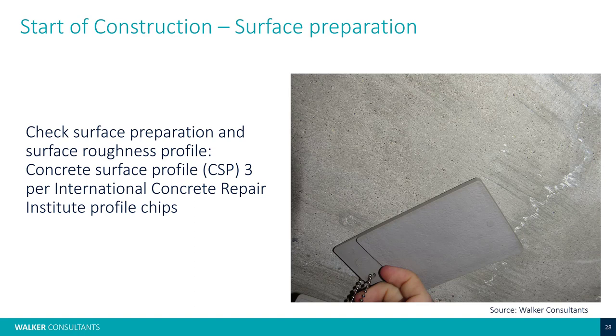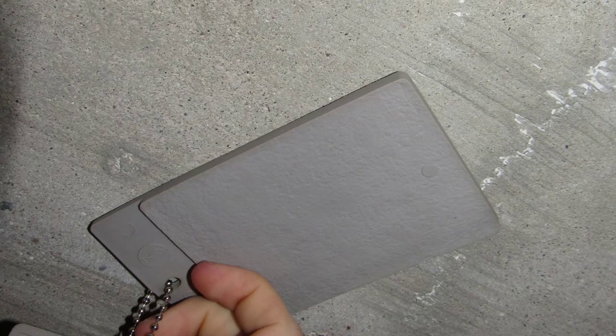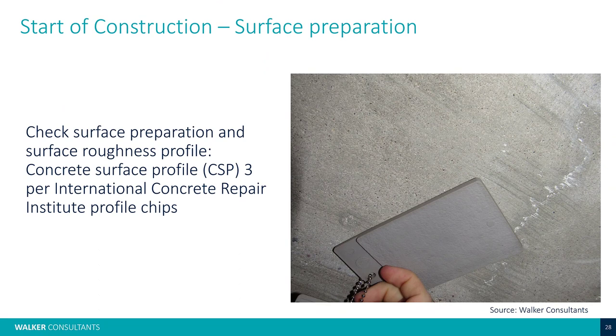Here's the surface preparation question. We want to check that surface preparation, the surface roughness profile. The International Concrete Repair Institute has chips, and you can take these chips out to the job site. So as any good engineer has, I've got a sample of the CSP chips, surface profile chips, with me. I put a little clip on the one for CSP3. That is the standard per ACI requirements, CSP3. You can work with your manufacturer if they want anything more or less.